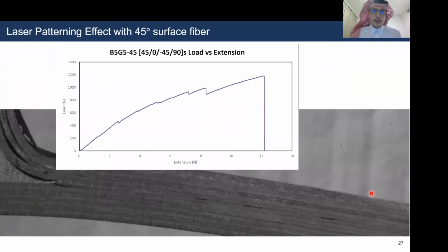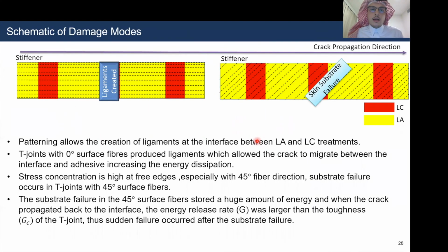So if I were to relate the laser patterning 45-degree load extension curve to the substrate failure that happened, we noticed that when the crack entered the substrate, this resulted in a huge extension through the skin. However, after it propagated out of the skin, sudden failure happened. And we can analyze the two different mechanisms of failure that occurred in those T-joint structures which experienced laser patterning.